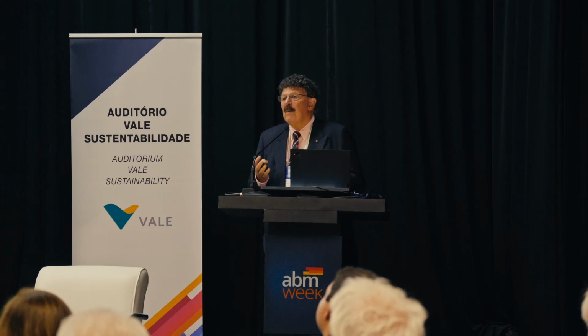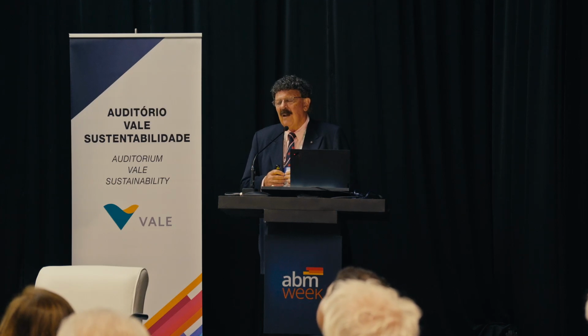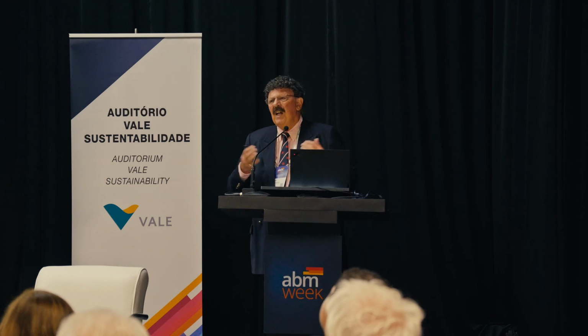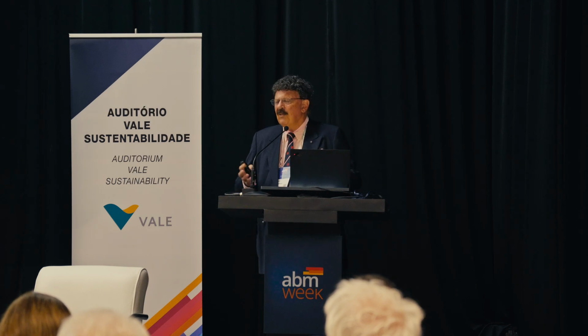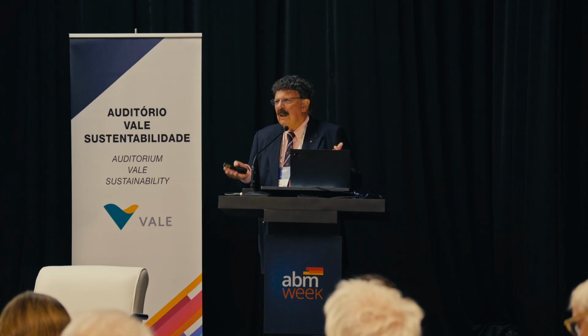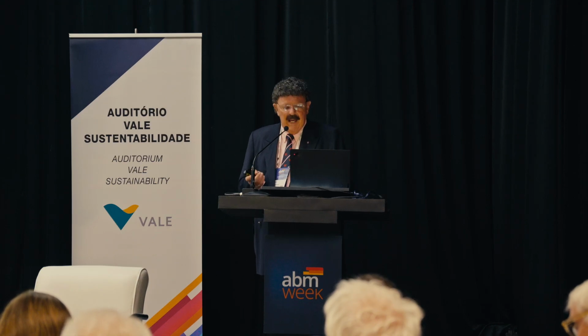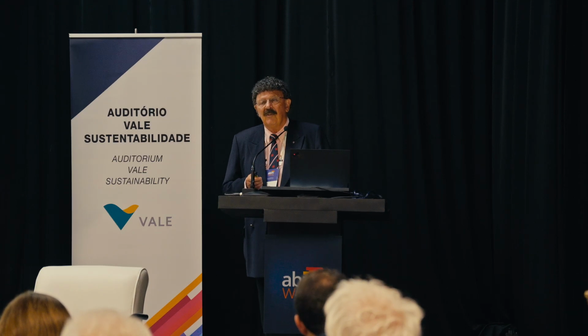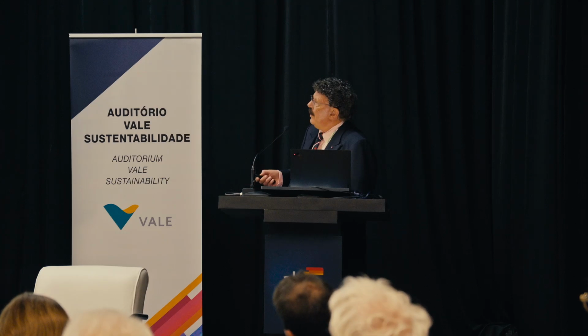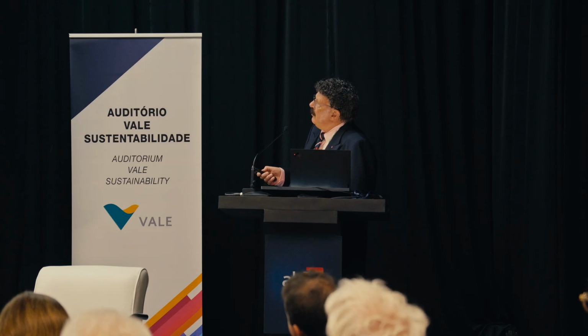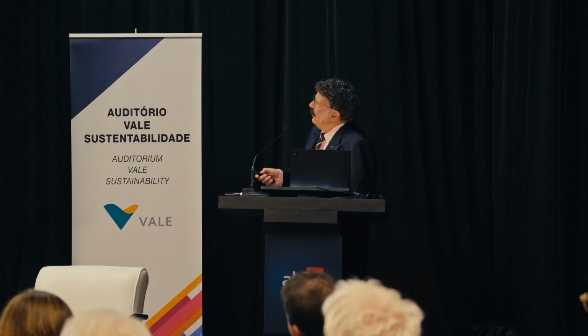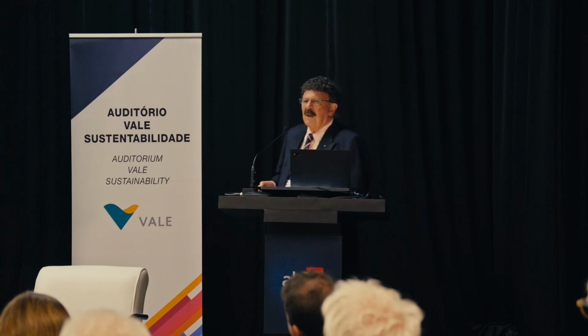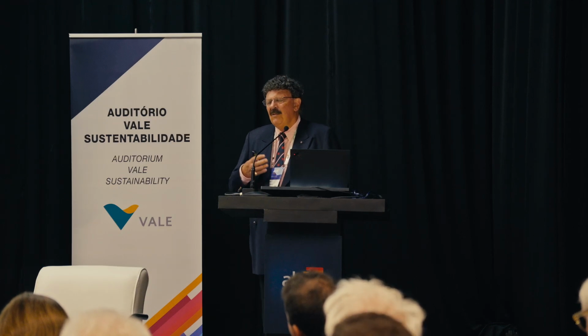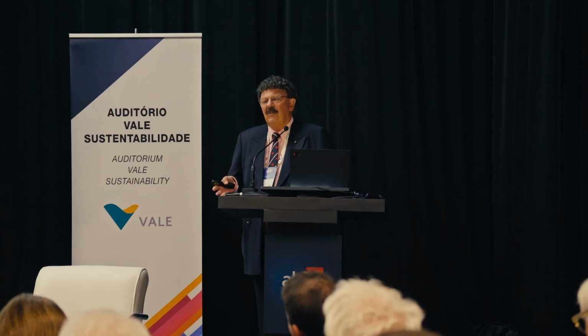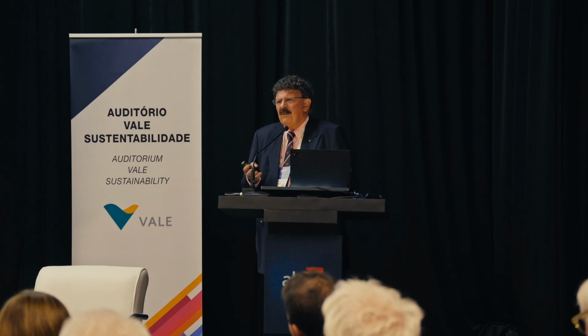So this is the problem with these refractory high-entropy alloys. Fantastic in compression, fantastic strength, very high temperatures, but any tensile properties, and they're brittle as hell. They have very high ductile brittle transitions. And in fact, this is the toughness data, and again, depending on what you're looking at, you're dealing with toughnesses well below 12 megapascal root meters, which is worse than the most brittle steel you can get. The most brittle steel is about 20.